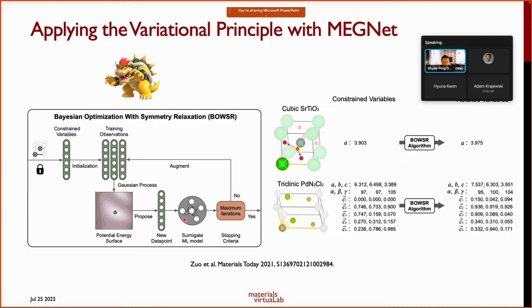It will just be slow. But obviously, because we have a good formation energy model with MEGNet, this is what we did. We basically apply this to take an initial crystal structure. So for example, let's say you have cubic SrTiO3. There's only one independent parameter. If you assume symmetry, that's basically just the lattice parameter, and the Bowser algorithm will relax that to 3.975.